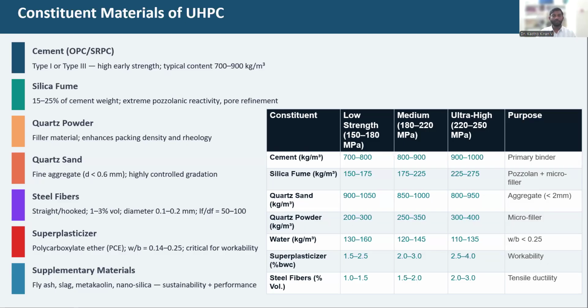And superplasticizers are one of the most useful materials in the preparation of UHPC, because flow is considered as one of the primary aspects. Particularly in the recent researches which are happening, self-compacting UHPC is gaining more prominence. So for that self-compacting condition, we need to use superplasticizers. Particularly the PCE-based superplasticizers are primarily preferred over the SNF or lignosulfonates or any other families of superplasticizers. And the critical superplasticizer dosage will range between 0.15 to 0.2 to 0.25. That's a typical dosage which will give a better flow. At least you can get 220 to 230 mm of spread diameter,